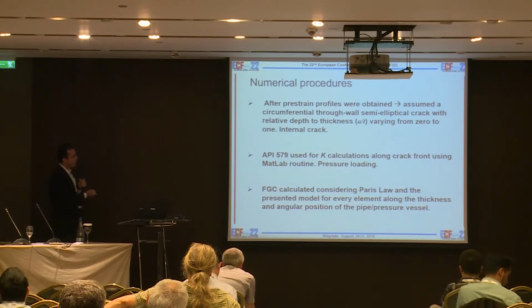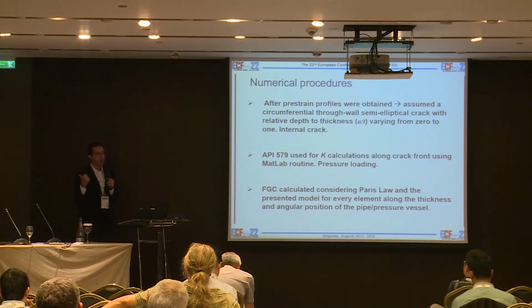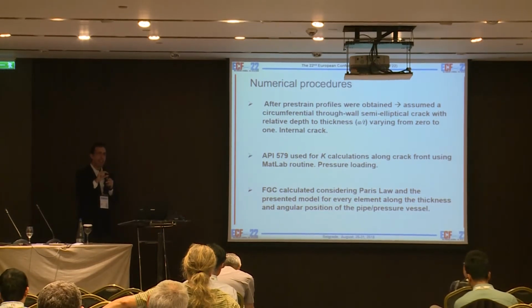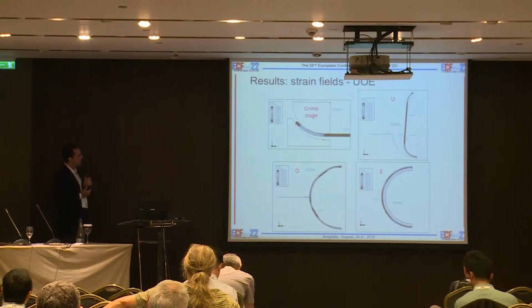And the fatigue crack growth was computed using the model I showed you right now for the A36. So we included the K solutions in the fatigue crack growth algorithm, and every time that the crack grew, it calculated the ΔK at that moment.